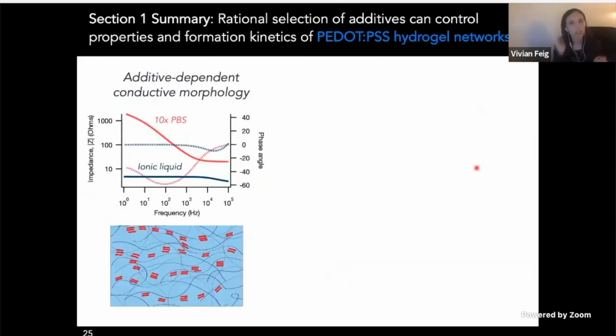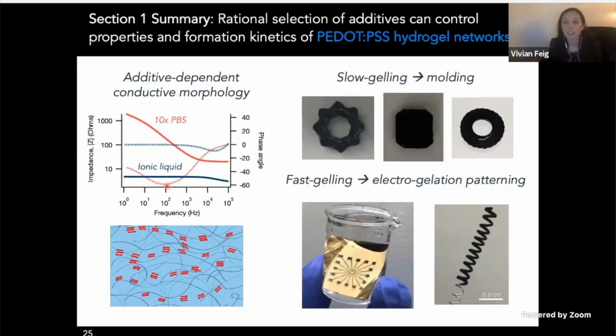So overall in this section, we see that one, through the rational selection of additives that can undergo this counter-ion exchange with PEDOT:PSS, we can form these soft hydrogels that also have really high electrical conductivities. And these additives also impact gelation kinetics, where slow gelling ions are really good for molding-based fabrication processes, whereas rapid gelation in the presence of these metal ions allowed us to come up with this new patterning method that not only creates high resolution feature sizes, but also these conformal gel coatings.